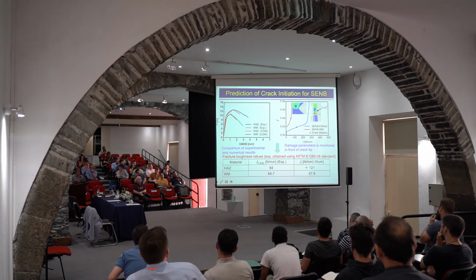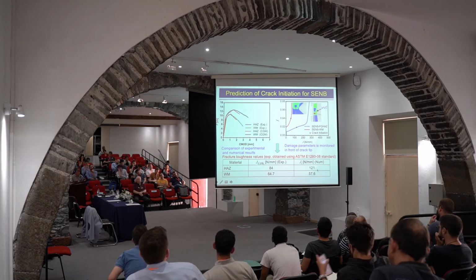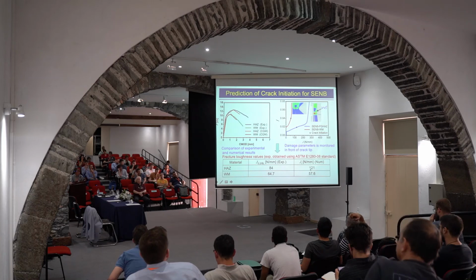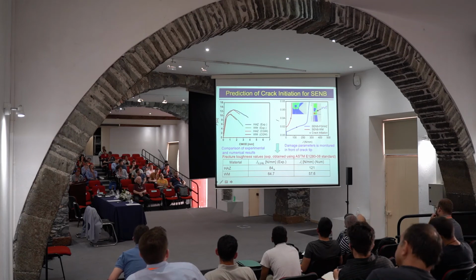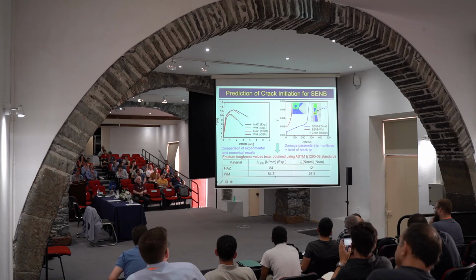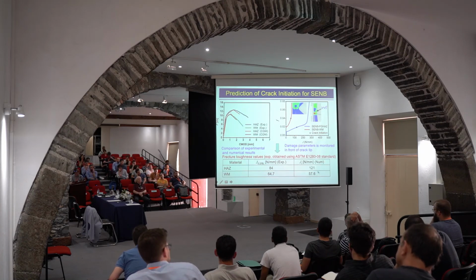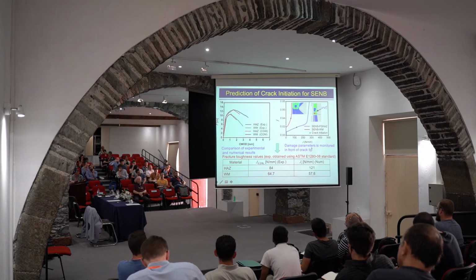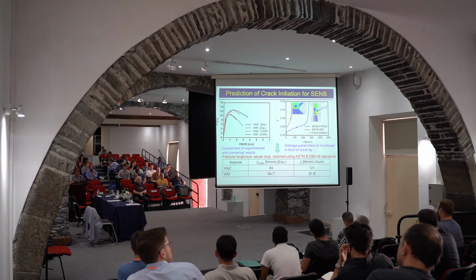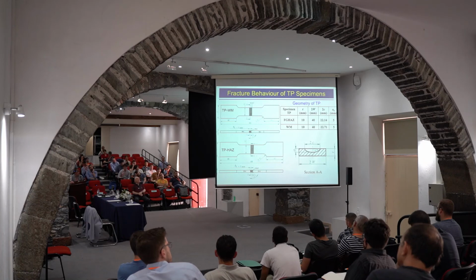So in the case of heat affected zone, our numerical simulation, micromechanical modeling, we got 121, and compared to the experimental results, 84, we thought it was good enough. In the case of weld metal, it was even closer, 65 approximately, corresponding to 57. Since this was the first time that micromechanical modeling was applied to a welded joint, we were quite satisfied with these results. In the case of tensile panels, it's about the same story, but in 3D.